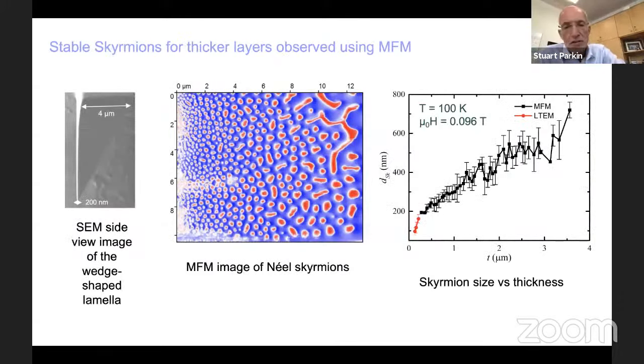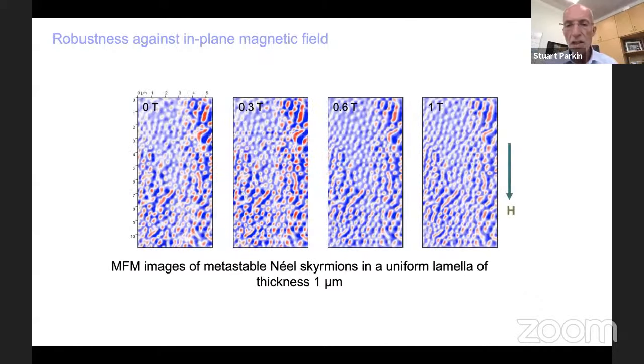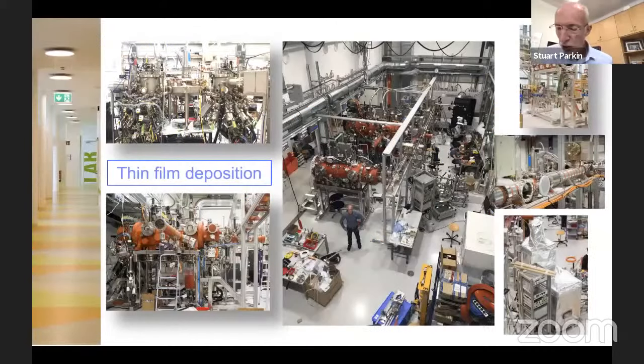And another very interesting aspect of these Néel skyrmions is, just like the anti-skyrmions we discovered, due to the particular symmetry of this trigonal symmetry, you find that, again, the dipole fields play a role, and the skyrmion size can be significantly evolved, with size varying here from 100 to 600 nanometers, as the thickness of the lamella is varied from a fraction of a micrometer to several micrometers. And this again is using magnetic force microscopy. This is some very nice work by Ankit. And it turns out these types of skyrmions are very robust to longitudinal in-plane fields.